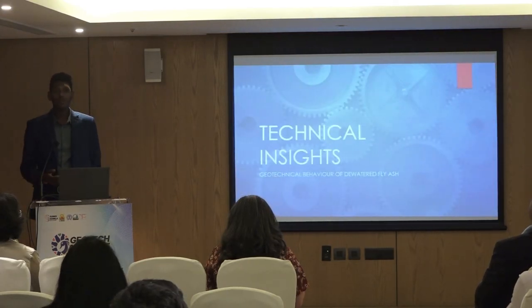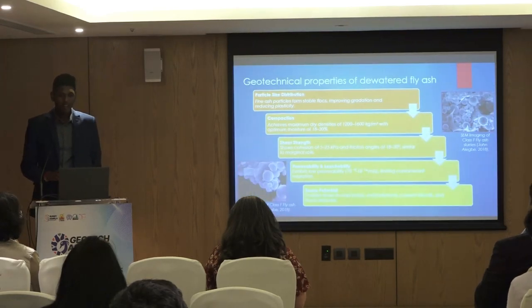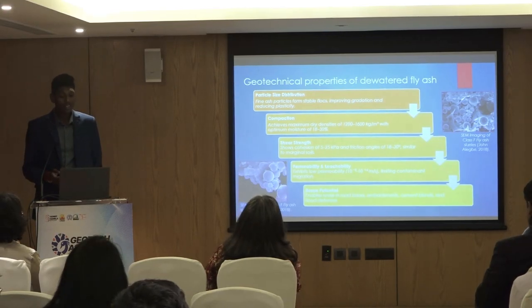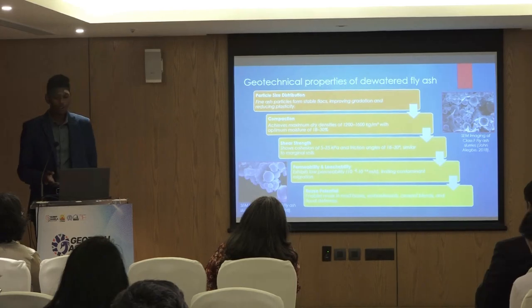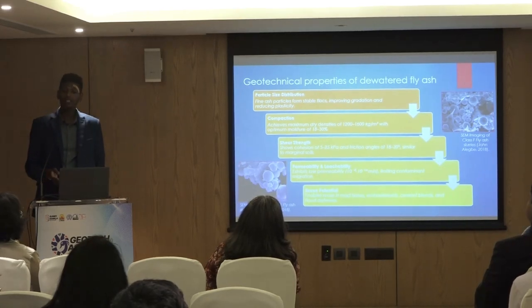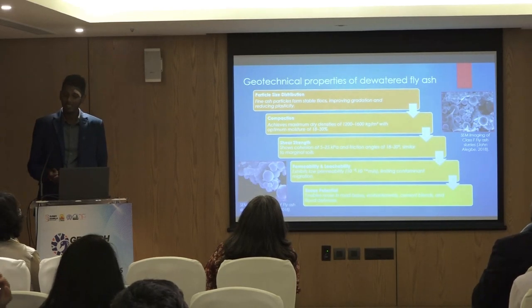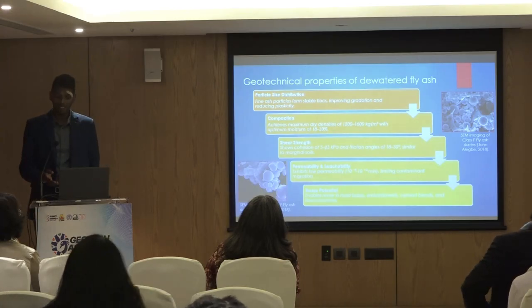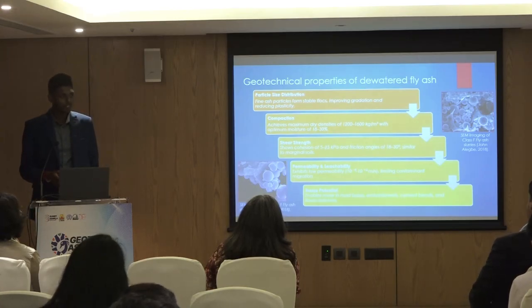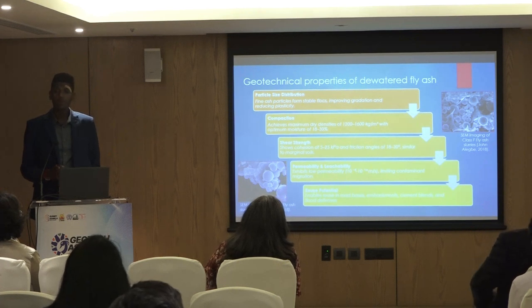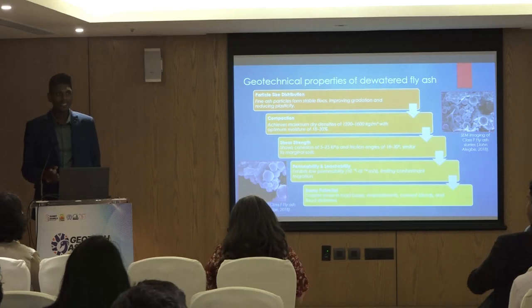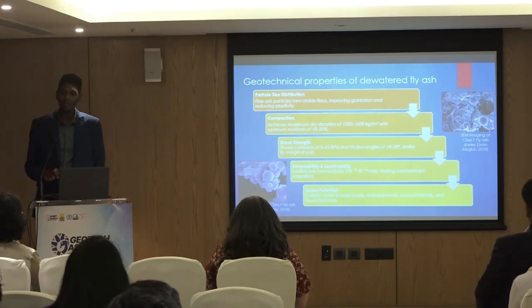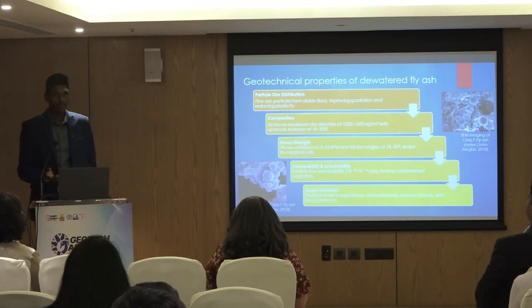So let's look at a few technical insights into this solution. Dewatering fundamentally changes fly ash. First, particle size distribution. Fines flocculate into larger aggregates, shifting the material towards well-graded silts or low plasticity fines. Second, compaction. Dry densities of up to 1.2 to 1.6 tons per cubic meter and moisture contents between 18 and 30% make it viable for engineered fills and road sub-bases.